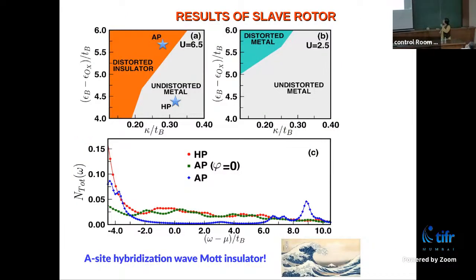Well, what we find is the following, that the strong correlation is equally important as the bismuth oxygen hybridization. And this is the value of the correlations we are trying to put. If the U parameter on the nickel site is small, these are all in electron volt, you have basically a transition between an undistorted metal to a distorted metal. By distorted metal, what I mean is big, small bismuth oxygen polyhedra, like a breathing distortion. If you make this U parameter large, this distorted phase indeed becomes an insulator.